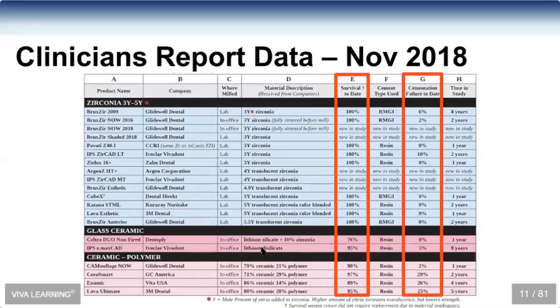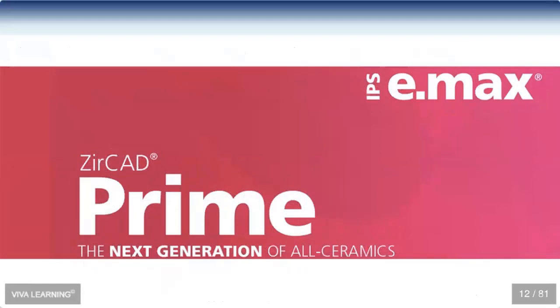And you look at something else like a lithium silicate product like the one above it, and even though it's got 10% zirconia, that Celtra Duo, after 1 year in the study, has already had 24% failure. So lithium disilicate is not the same as lithium silicate, even though it sounds exactly the same except for those letters D and I. You want to make sure that when you're choosing a lithium disilicate, you're choosing truly a lithium disilicate. Well, I'm happy to announce that there's a new member to the Emax family.